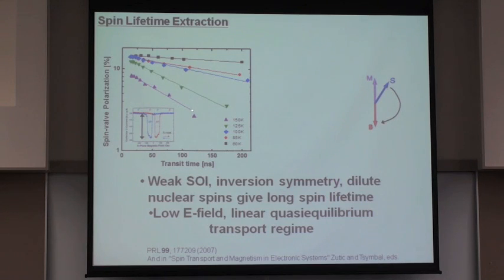And what we see is that as we increase the electric field, the transit time decreases, but the polarization rises. This, of course, is due to a finite spin lifetime. And we can fit these data points and determine the time scale for spin depolarization. That's our spin lifetime.